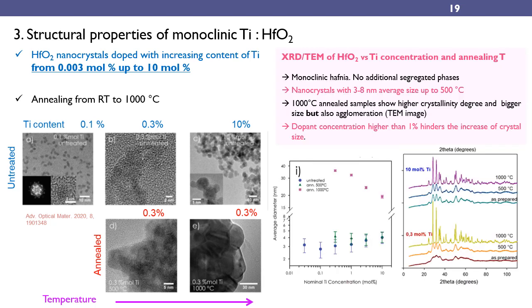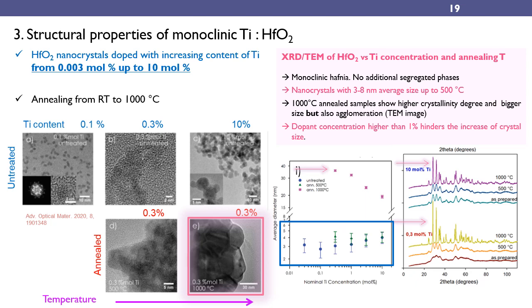TEM and XRD measurements reveal that the monoclinic hafnium nanocrystals have a size of 3 to 8 nanometers for annealing from room temperature to 500 Celsius degrees. Titanium concentration does not influence the size nor the monoclinic structure. When temperature increases, the growth of one order of magnitude of the crystal size occurs, together with the agglomeration of the crystals, due to the decomposition of organics from the crystal surface. However, high-temperature annealed samples doped with contents of titanium higher than 1% show a decrease of the diameter.